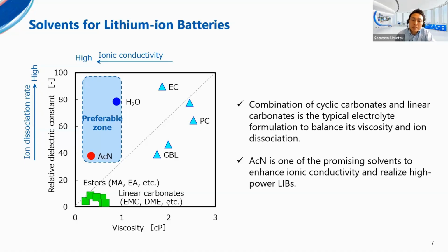Ethylene carbonate, EC, has a very high dielectric constant, but because of its high viscosity and its melting point, it is usually used as a mixed solvent with linear carbonates. Acetonitrile is one of the promising solvents to enhance ionic conductivity and realize high-power lithium-ion batteries. In recent years, esters have been used to increase the ionic conductivity of electrolytes. Methyl acetate, ethyl acetate, and other linear esters are located on the lower left side in the graph and have lower viscosity than linear carbonate.